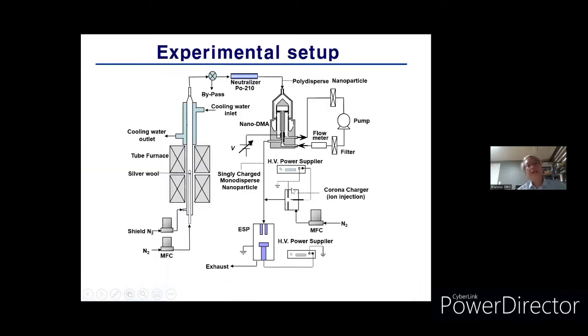This is our original experimental setup, very early time. So we generated silver nanoparticles using tube furnace, passed through neutralizer and nano DMA, select singly charged monodispersed silver nanoparticles. In our experiment, we selected around 10 nanometer singly charged silver nanoparticles.